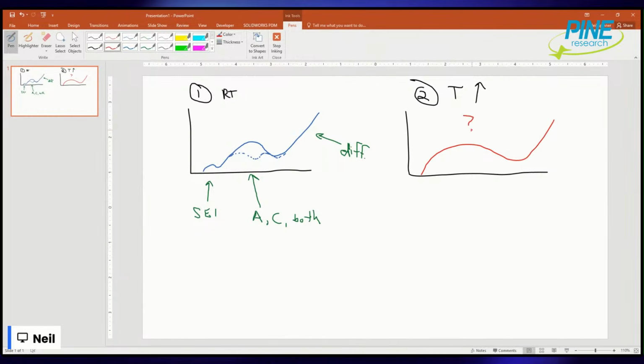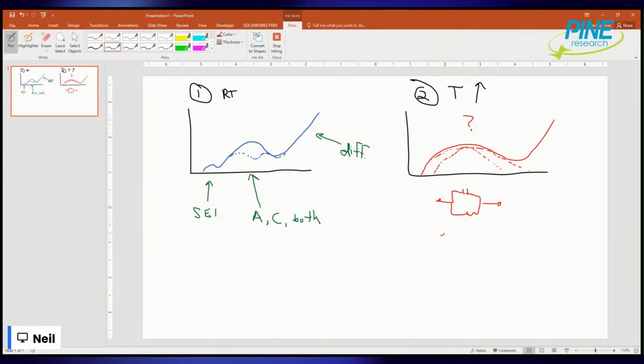All right. So one reason could be, as you said, time constant. What actually might be happening is almost like deconvoluting 2 semicircles. I'm drawing really poor semicircles, mostly because my art skills are terrible. But you could imagine if I superimpose 2 semicircles, they would almost overlap. And so it manifests as one semicircle. So should I fit this with one RC or RQ, or would it be 2? This would be 2 semicircles, but the time constant here.